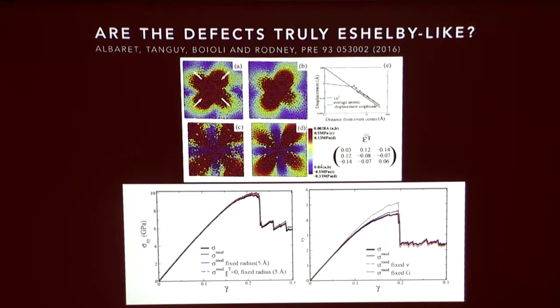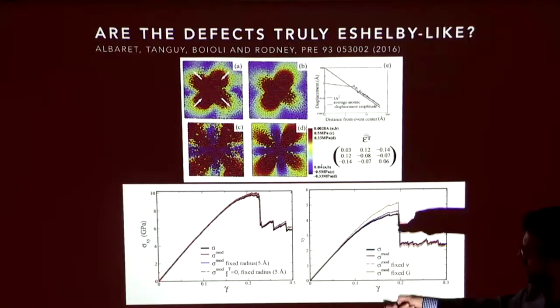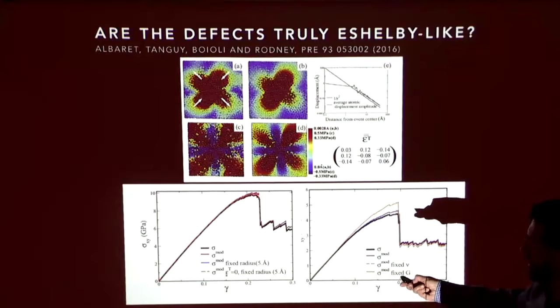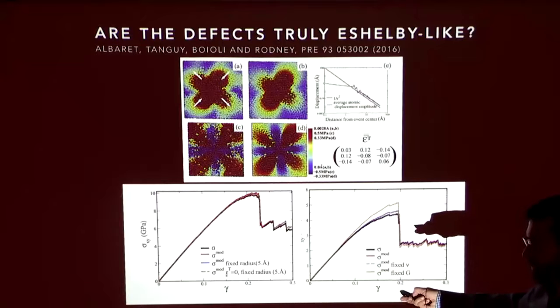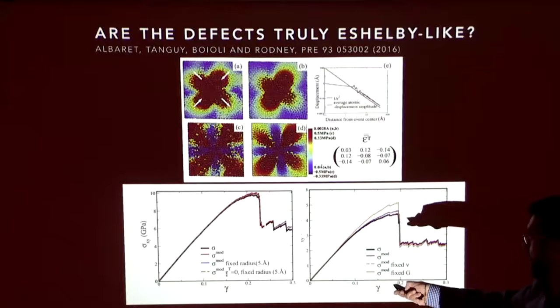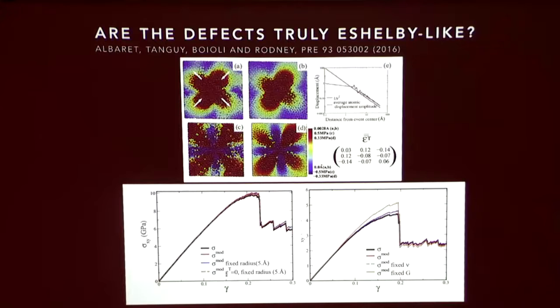So is this probably in the not-elastic branch, but in the branch before the union? Well, here they have both. Here it's more or less elastic, then you have some sort of hardening regime, then they get softening, where there's some more profound stress going on, probably some amount of localization. This particular image is probably from a very small strip, maybe taken from around here.